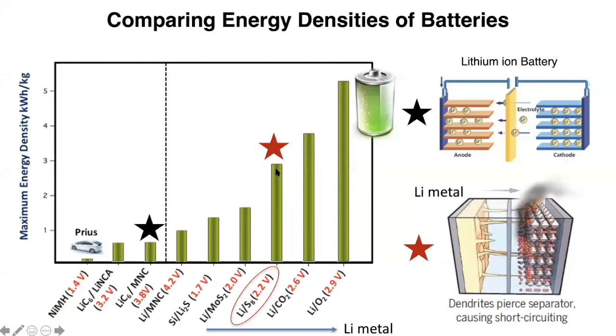So in order to get this high energy density, the graphite is removed. There's only pure lithium. So you take away some weight from the anode, and it's pure lithium. But the problem is there's no host to protect the lithium to make it stable. And when lithium metal is formed, by an electrochemical reduction of lithium ion, it cannot grow in a very controlled way. It forms these dendrites. There could be some non-uniformity. And as soon as there's a spot that's non-uniform and potentially a place where ions can accumulate very quickly, then the growth becomes very rapid and forms these dendrites.